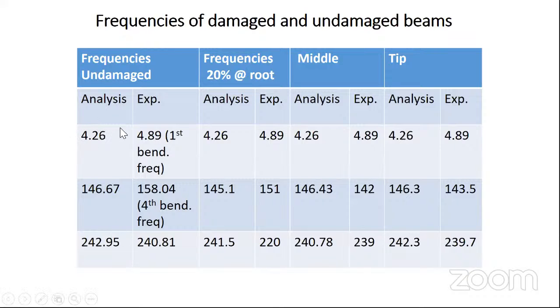If you see, these are the frequencies of the undamaged one. Basically, we can't find anything from the twisting mode or lead-lag mode, so I have only focused on the bending modes. The first frequency is 4.89, and from the analysis it is 4.26. We are very close. If 20% of the root area is delaminated, you can see not much change in both the analysis and the experiment. If you see the fourth mode, the variation is a little bit more.